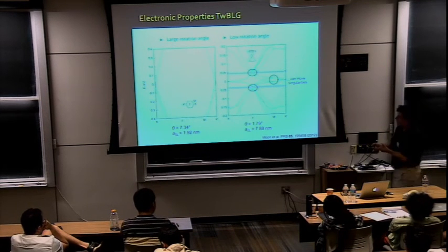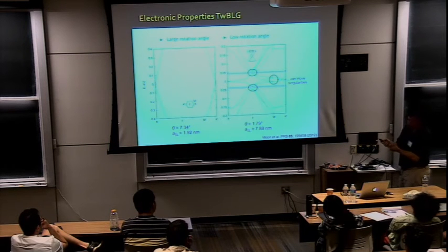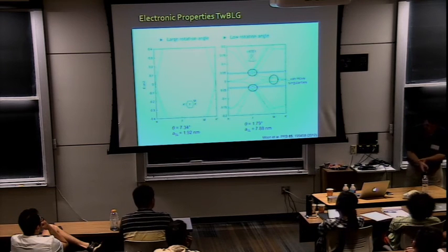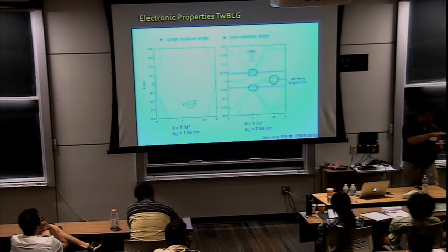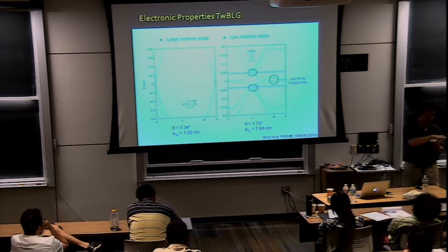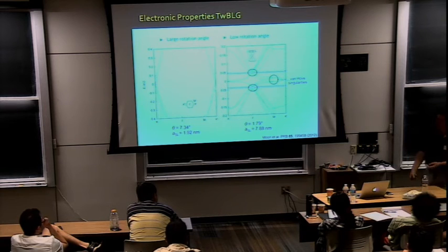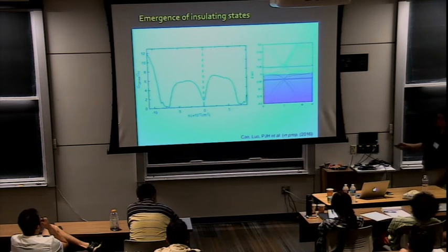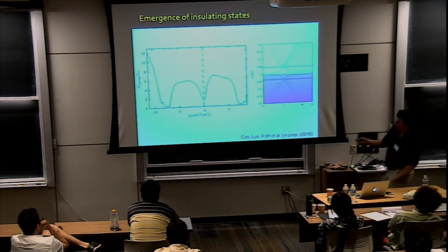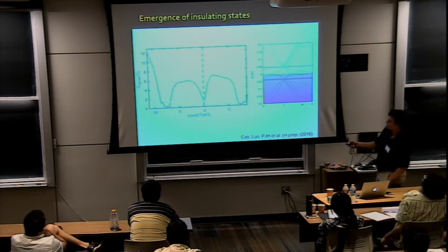Okay? So just to show you what happens, some data, let me show you something. I'm going to show you that if you put the best conductor in the world at high density, conducting very well, on top of the best conductor in the world at high density, conducting very well, you get an insulator. Okay? So this is what this can show you. This is the conductance versus density of one of these small twist angle layer graphene. Here you have the low conductance, this in e squared over h units. So you see about 2 e squared over h here near the original Dirac point.